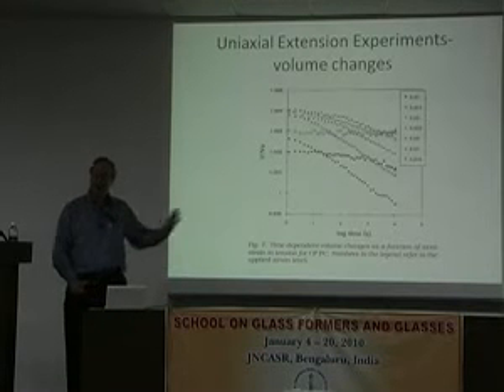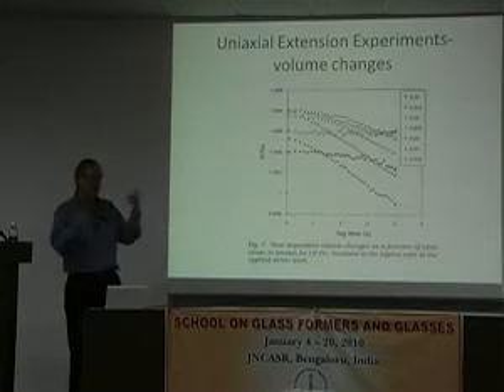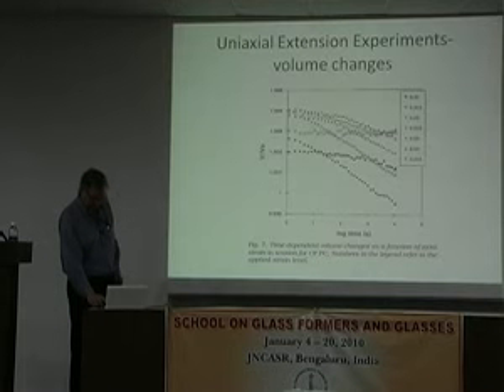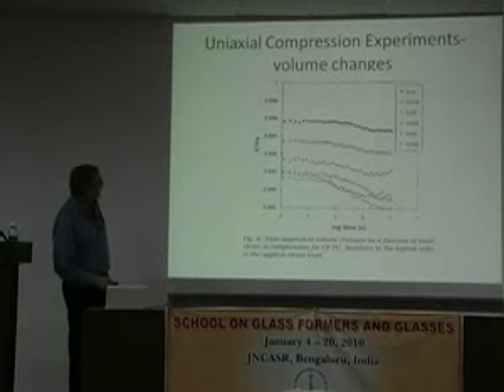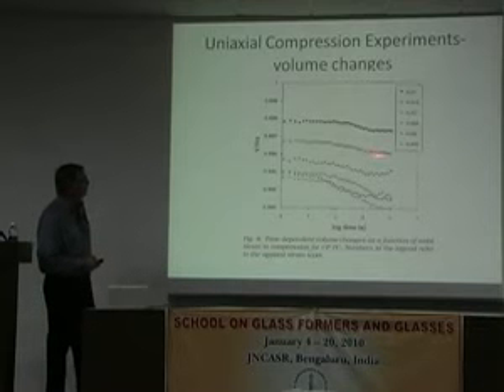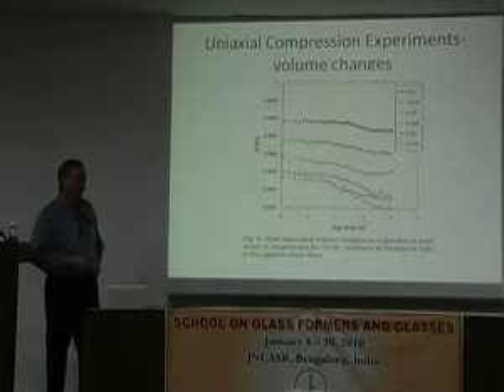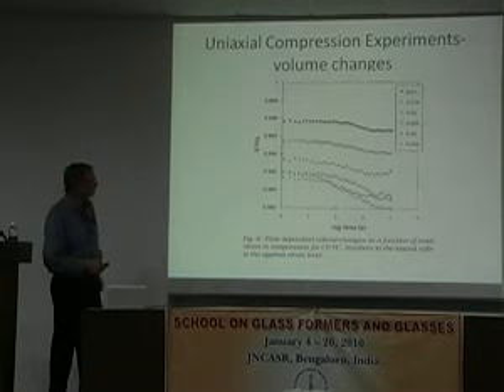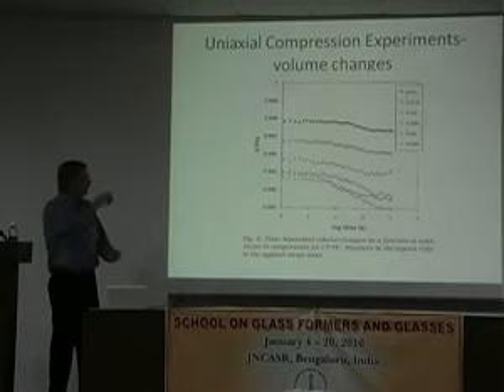Now this is 120 degrees below the nominal glass transition in this polycarbonate. The other thing that was interesting was that when we did compression, we couldn't go to as high strains in compression because we would buckle the sample.